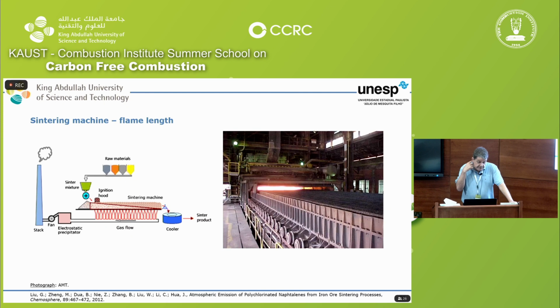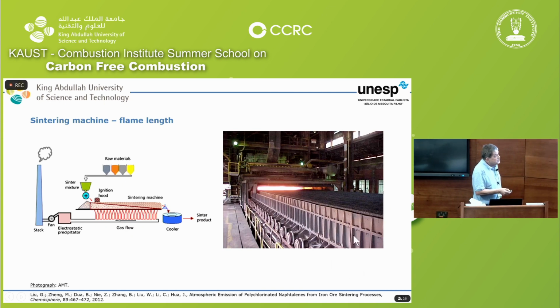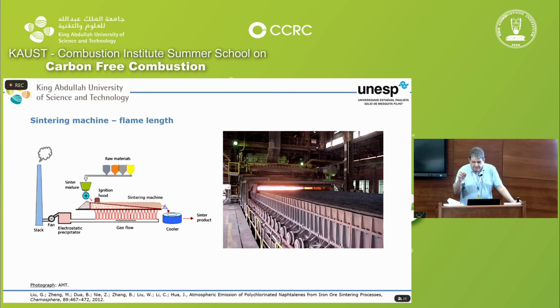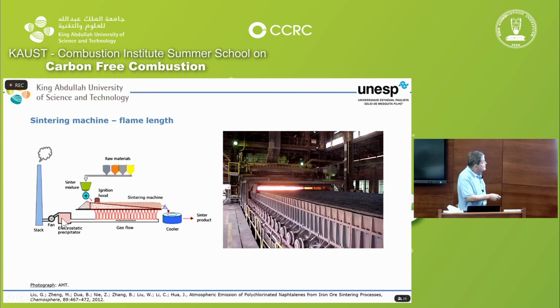The biggest problem of this sintering machine, you see, there is this thing. Oh, this goes this way, okay? And you have a combustion wave in here, a smoldering combustion wave, and you have the sinter, what they call sinter. In this case, you have particles of carbon and air passing. In the place where the particles are, you have rich combustion. And outside of the particles, you have lean combustion. And sometimes you have an explosive mixture that burns in the electrostatic precipitator. You have to be very careful, okay?